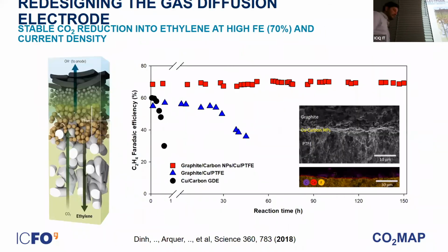Now, these catalysts showed high performance, high Faraday efficiency, and high current, but they were not really stable. You can see how here these black circles represent the Faraday efficiency for ethylene versus time. You can see how within the hour the performance is lost. So we thought, okay, what's wrong? And we figured out that controlling the hydrophobicity and hydrophilicity in these gas diffusion electrodes was crucial.